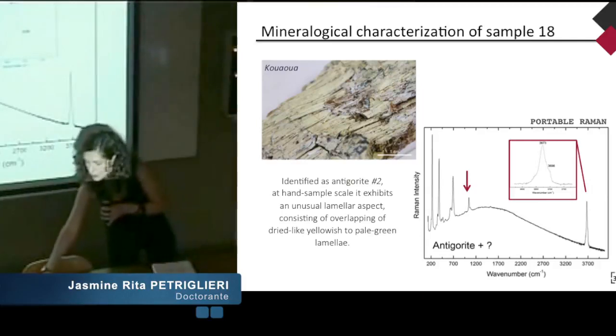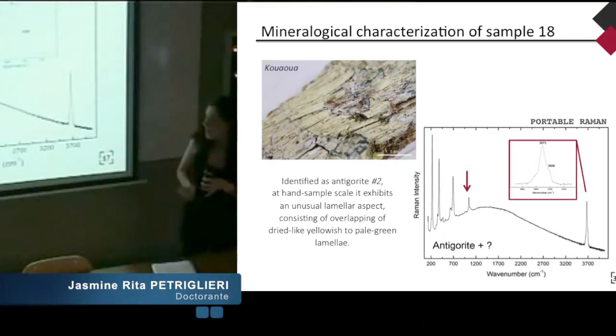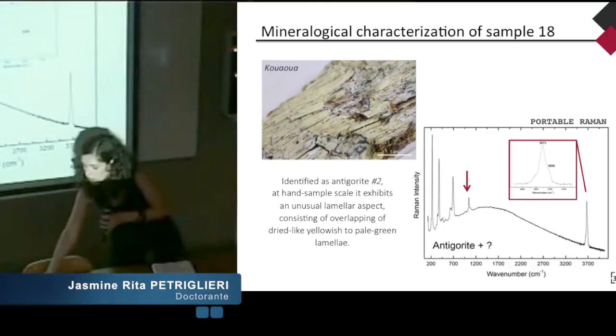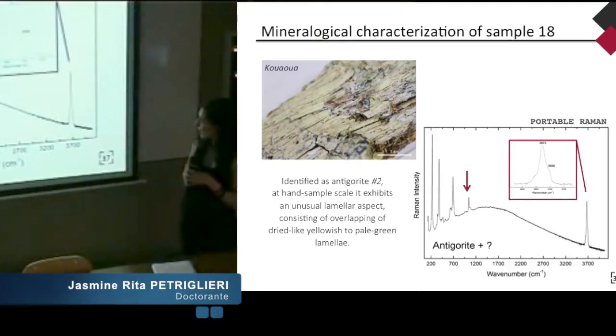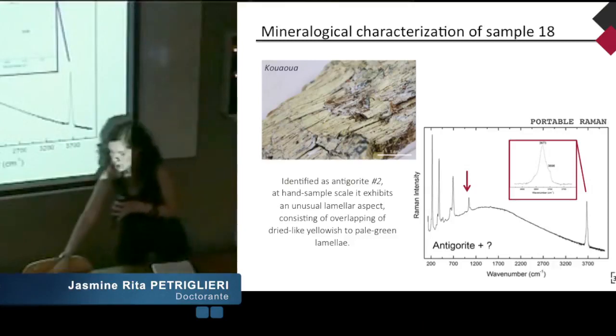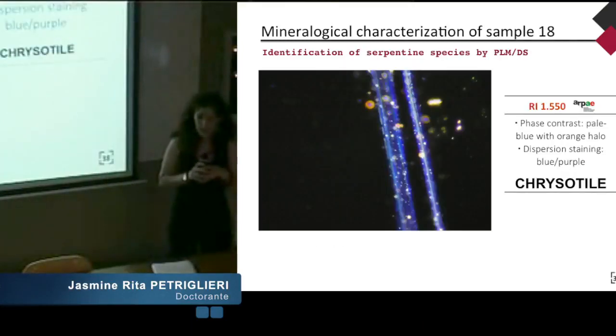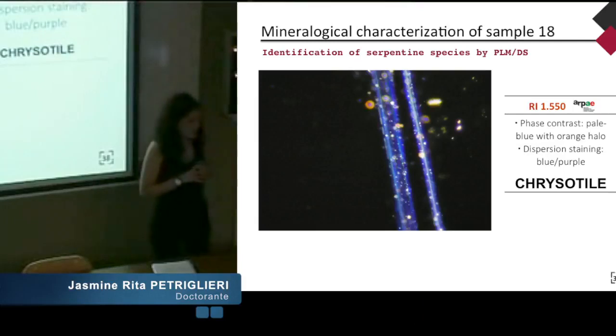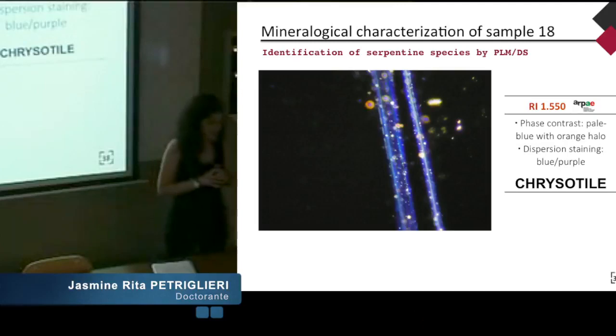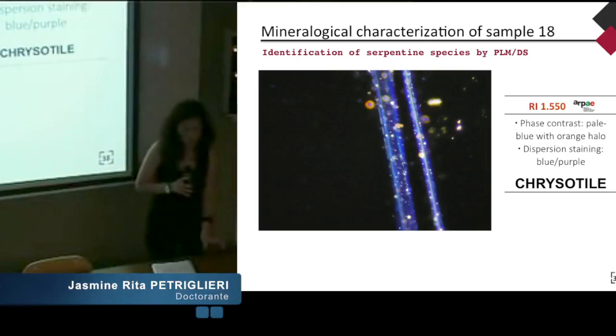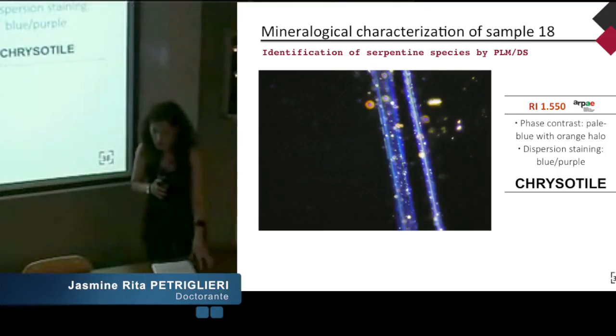Preliminary results obtained with portable Raman demonstrate that at the lower wave numbers we observe the typical Raman peaks of antigorite. Conversely, observing the OH stretching vibration, the doublet of antigorite is shifted to higher wave numbers. This suggests the presence of secondary and other serpentine minerals. To study this sample by optical microscopy associated with dispersion staining, we need a minimum of two refractive index liquids, one for the chrysotile and one for the other variety of serpentine.